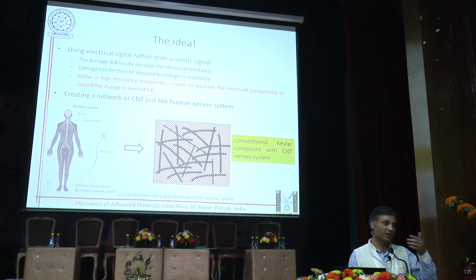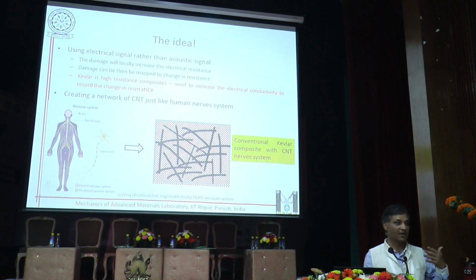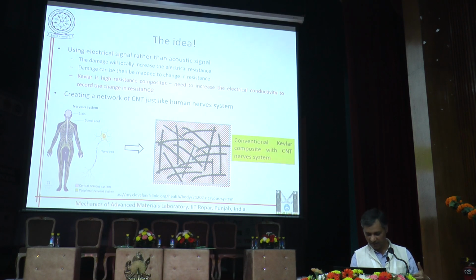So first we need to work out basically in terms of the resistance. So we need to improve the conductivity of the Kevlar, or decrease the electrical resistance of the Kevlar. On the other hand, you have a CNT, which is a very highly electrically conducting material. It has very good electrical properties, optical properties, and almost all properties are good, right?